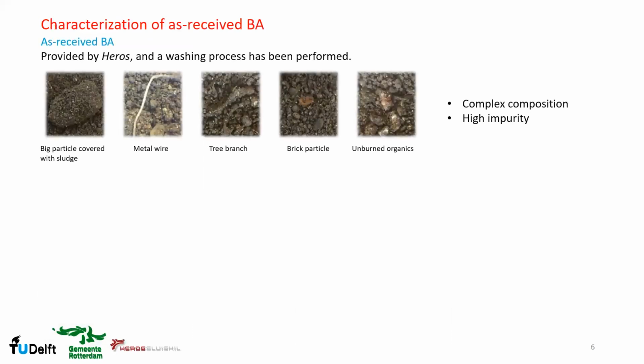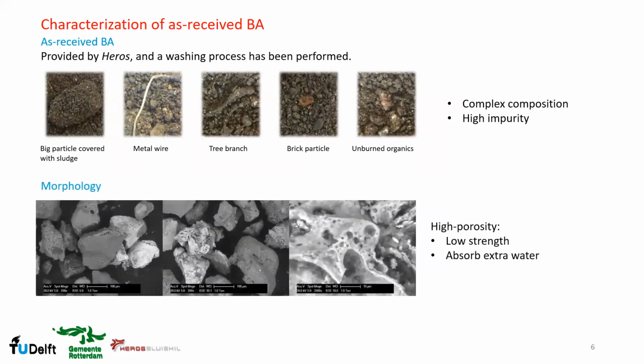In this study, the bottom ash is provided by a Netherlands company, and they have performed a washing process before delivery, and we see there are still a lot of impurities, and the composition is still very complex. The morphology detected by SEM shows a very high porosity microstructure, which will result in the low strength of particles. On the other hand, the pores will act as water reservoirs. They will absorb extra water in the fresh cement paste. So pretreatment should be done before they could be applied as a substitute material in Portland cement.